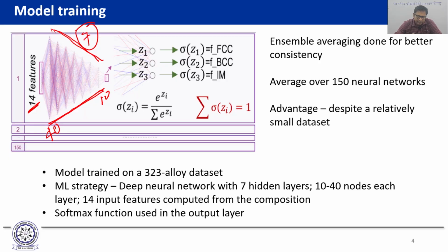So you have to take measures to avoid this overfitting challenge, and there were a number of things that can be done and that we did in this particular model, and one of them is to take an ensemble averaging type of approach. So what do I mean by ensemble averaging? It means that I have sampled different parts of the data set, and I have made a large number of models. So we made lots and lots of neural network models. About 150 different ANN models were made with the same data set, sampling the data set differently. And after you make this large number of models, what you basically do is you average the predicted value over all of these neural networks.